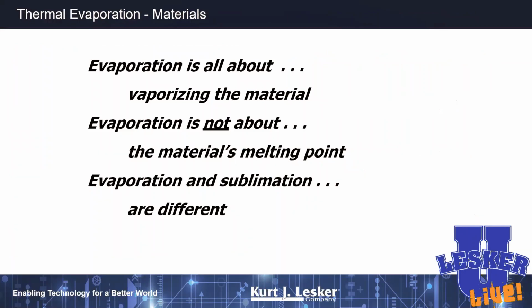Okay, so again, when I talk about thermal evaporation or evaporation at all, it's about vaporizing the material. Thermal and e-beam evaporation is really not about melting the material. So we're interested in the melting temperature because it's going to have some effect on how the material is going to react with our boats, but we're really not intentionally trying to melt anything if we can get away with it. And evaporation and sublimation are different. So evaporation we're going to do with heat. Sublimation we can just do with pressure. So I'll show you some charts in a couple of seconds where we can just sublime something if we want to make a film out of it.